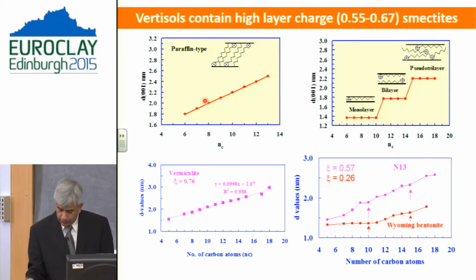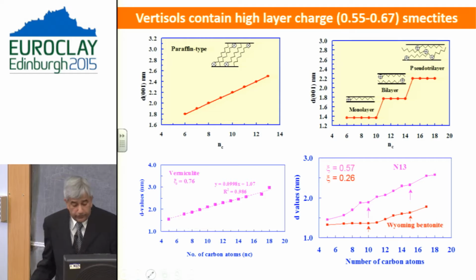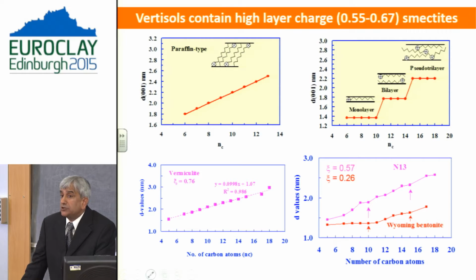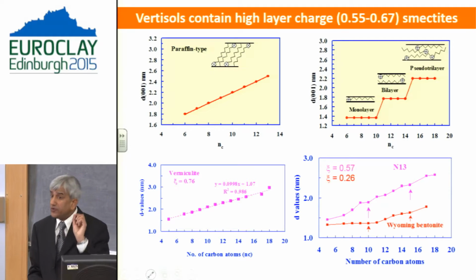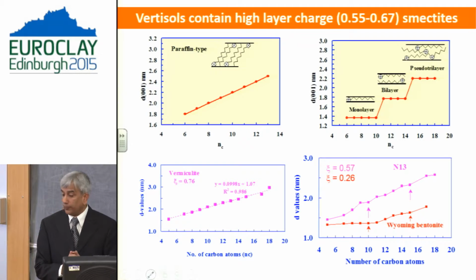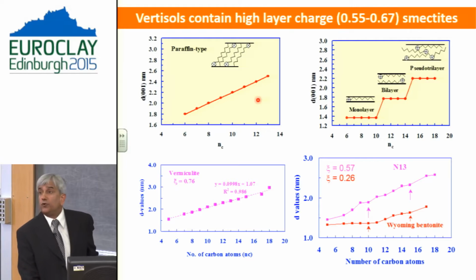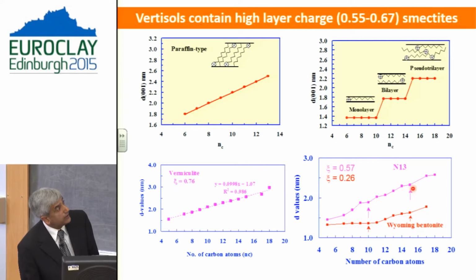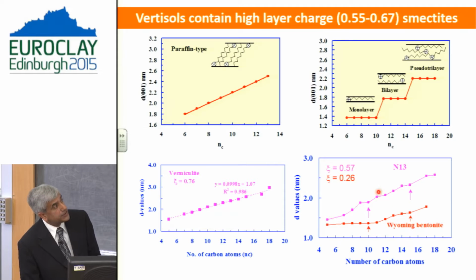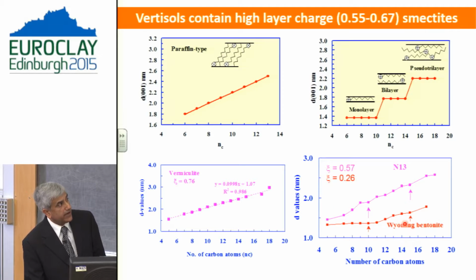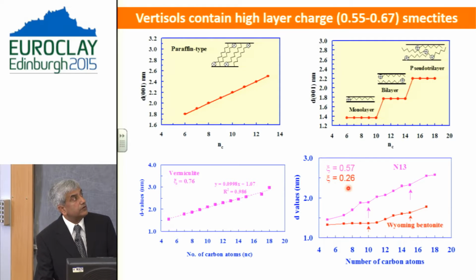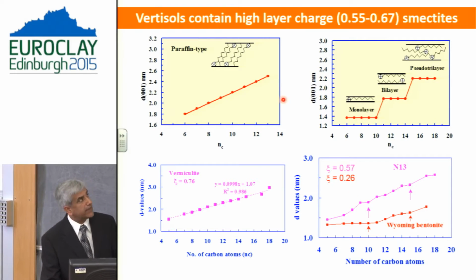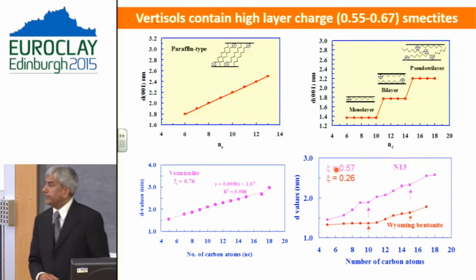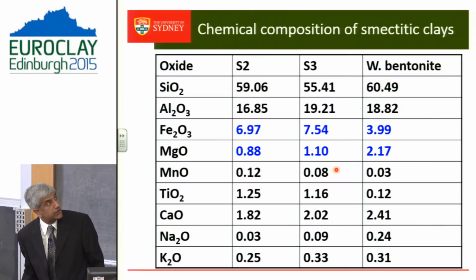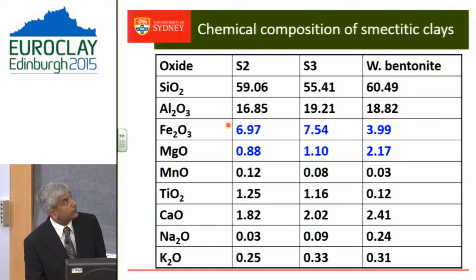The point I want to make in case of smectite, in case of vertisol, is that a lot of these vertisols have smectite-dominated clay mineralogy. And the smectite is different from the smectite we are often used to, the Montmorillonite type of smectite. Here we measured the charge of these smectites in soil. If you look at this right panel, this is one of the soil smectites, N13, and here in red is your Wyoming bentonite. The charge in Wyoming bentonite is about 0.26, whereas the smectite in soil has a charge of nearly 0.6. So much greater charge in smectite. Also, the smectite in soil contains a lot more iron and a lot less magnesium.